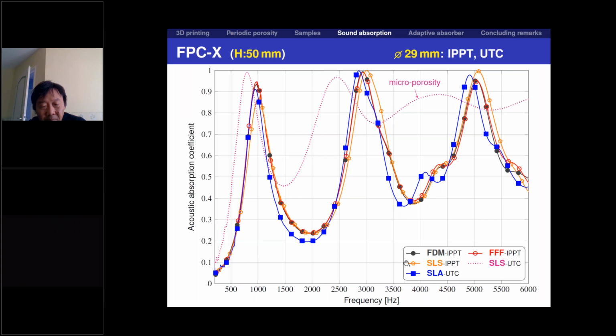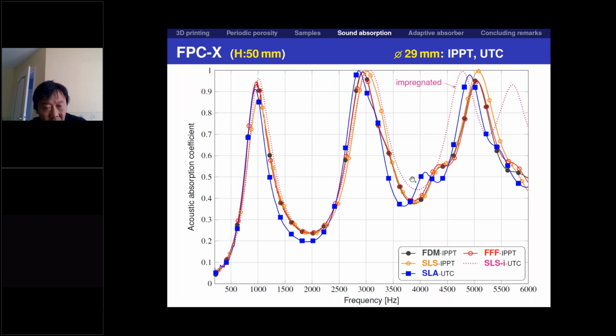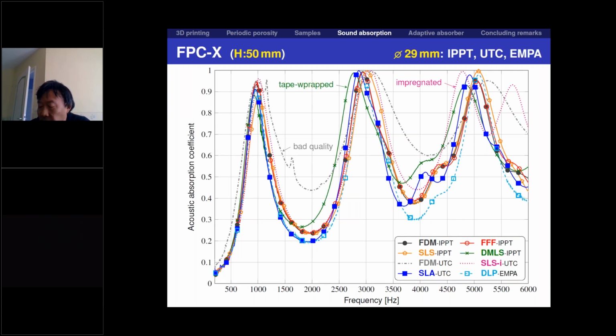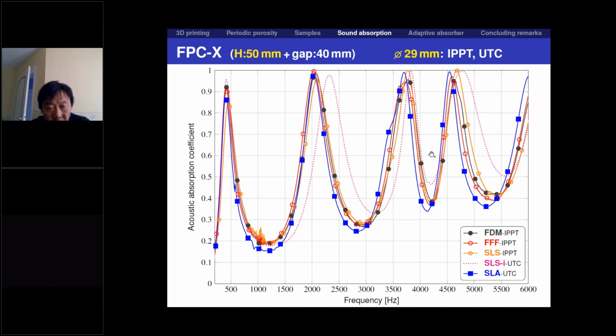And now maybe the most interesting results. These are samples sintered from a polymer powder of larger grains than we used, and there was microporosity involved. So UTC impregnated the samples and measured them again, and you see that the curves are very similar, only at the highest frequencies they have some discrepancies, which was expected. All the curves compared together, and now the absorption curves for the sample with an air gap between the sample and the rigid termination in the tube.